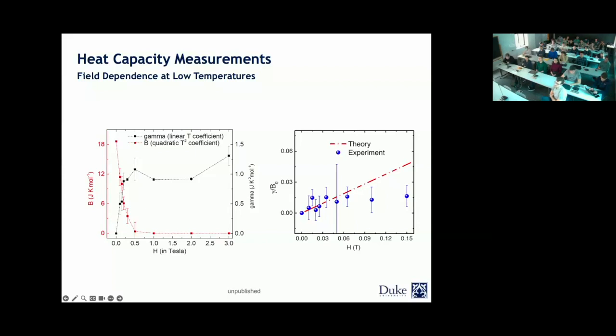However, we also calculated this ratio and compared it to the theoretical value that Patrick's paper predicted. Here is what you're seeing. This is our experimental data, which within the low field region follows the values you would expect from the theory. And when we go to higher field, it starts to go off. So that was an indication that this also agrees with what we are seeing here as well. The values are in good agreement.